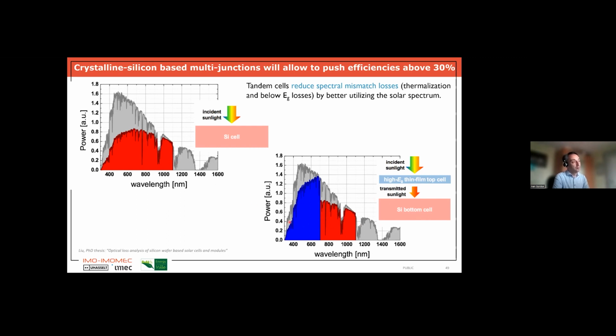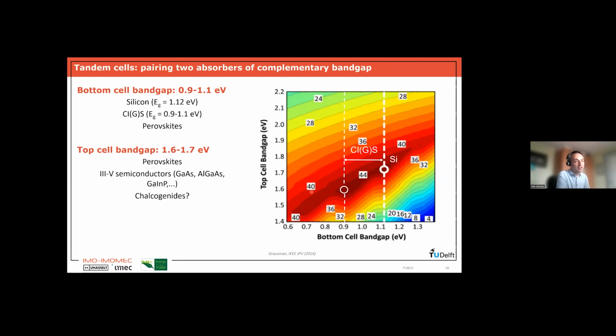But the blue light, the high energy photons that are absorbed in the top cell, because the band gap of this material is higher, we will use more of their energy. So we lose less. The gray area here is smaller than what we have here. And this will allow in the end to have two cells on top of each other, which we call a tandem, that has a higher efficiency. We can calculate the theoretical efficiency limits for such tandems, and it depends strongly on the band gap of the materials. So you have to select two materials to put on top of each other which have matching band gaps.